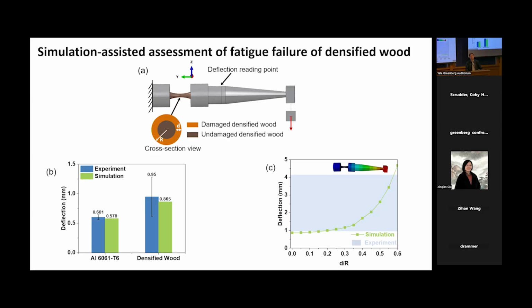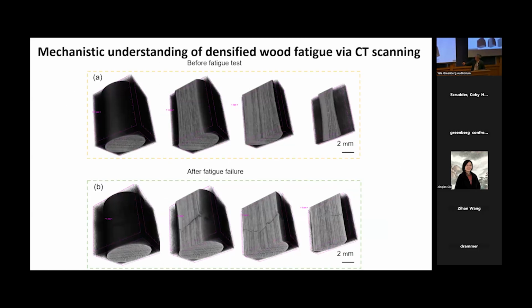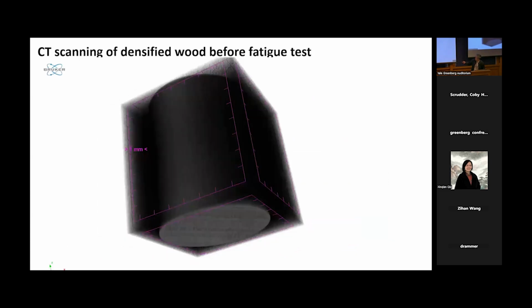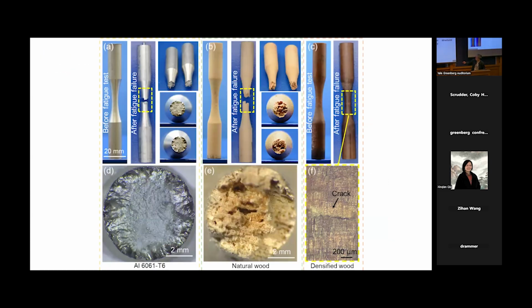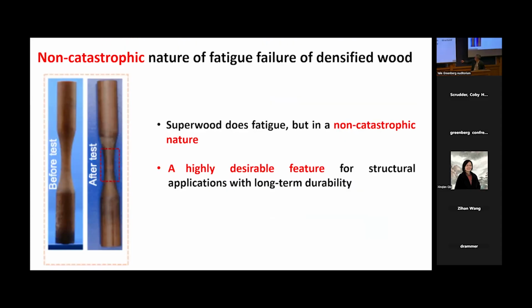So have you looked into the residual strength? Let's say when you call it fatigue failure, how much residual strength does it have? Yeah. We didn't measure that, but we can do that. If you look at the unfailed sample, well, it's failed by fatigue, but like this one, if there were any residual strain, it's quite local. The dimension of this doesn't really change too much, and the diameter almost. By looking at this, if I don't label those, you won't be able to tell the difference of these two.